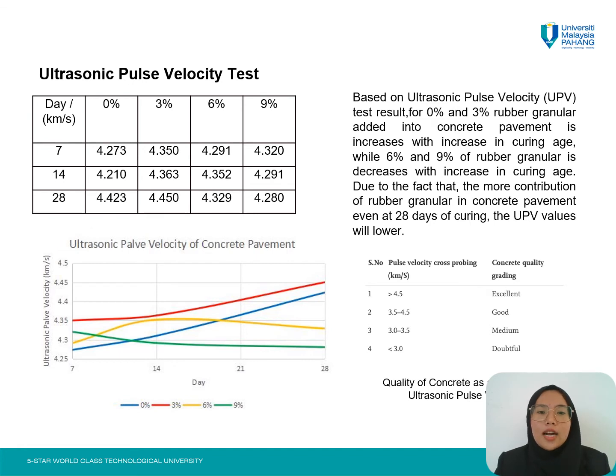Then this is the ultrasonic pulse velocity test. Based on the ultrasonic pulse velocity test result, for 0% and 3% rubber granular added into concrete pavement, the value increases with increase in curing age, while for 6% and 9% rubber granular it decreases with increase of curing age. Due to the fact that the more rubber granular in the concrete pavement, even at 28 days of curing, the UPV test value will be lower.